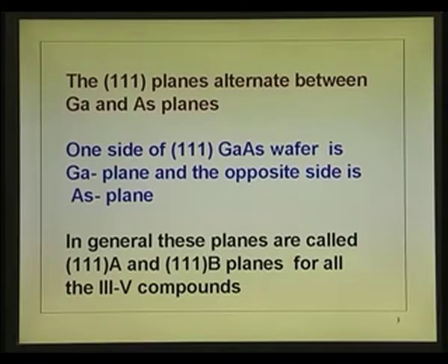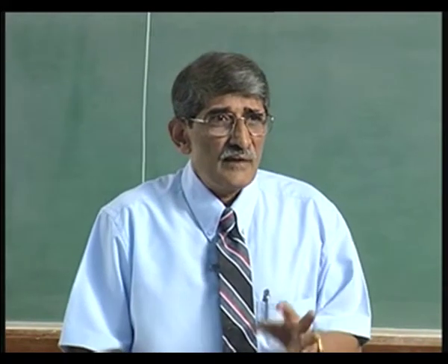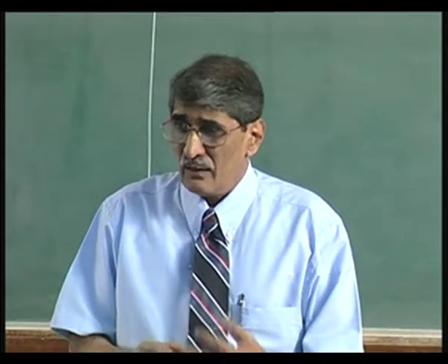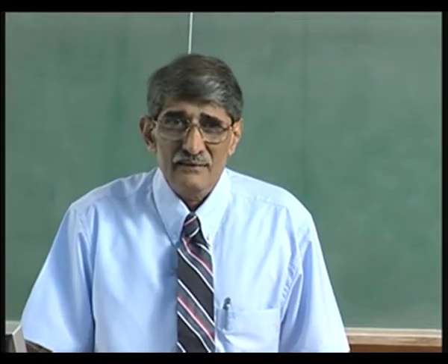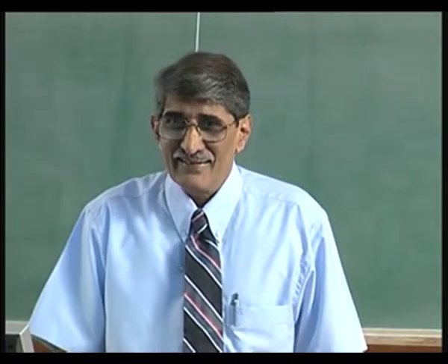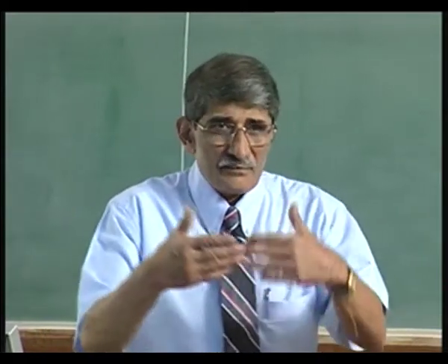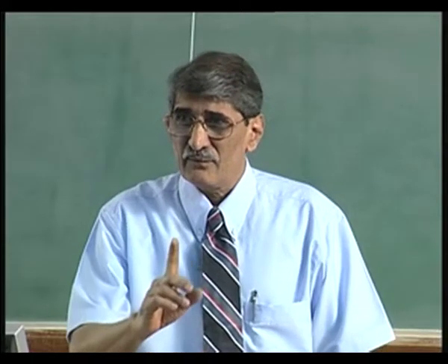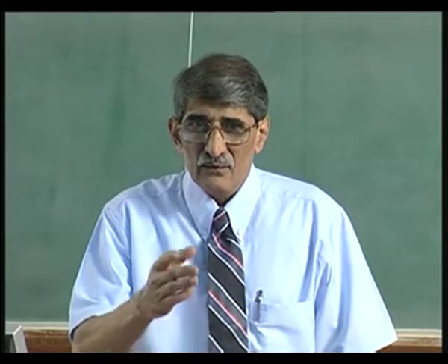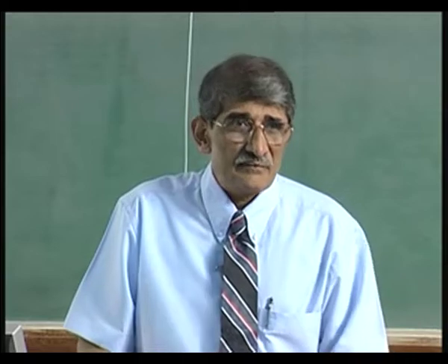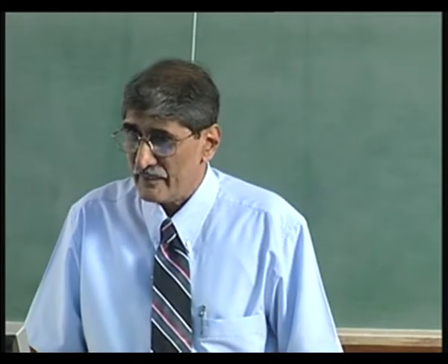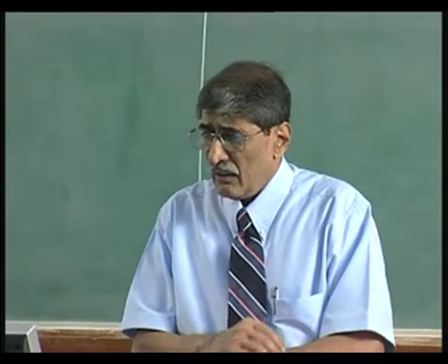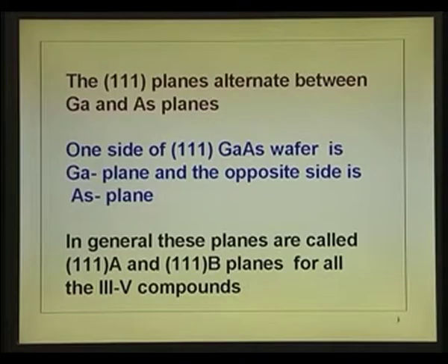These are some of the consequences of the peculiarity of the compound semiconductor. In silicon, it does not matter. Whether you take the top face or bottom face, 3 are bonding there, 1 is available for chemical reaction. So, whether you take top or bottom, it oxidizes the same way, you can polish both in the same way. These are some of the major differences, apart from the crystal structure, the reactivity of the surfaces.